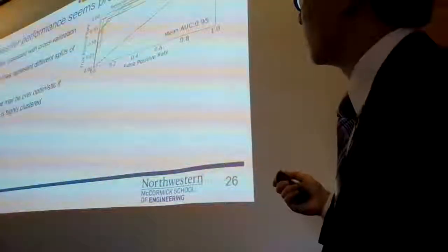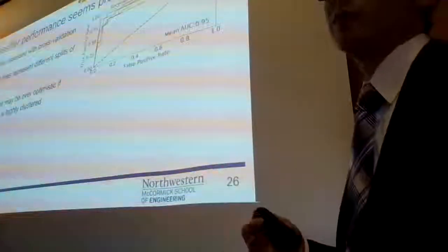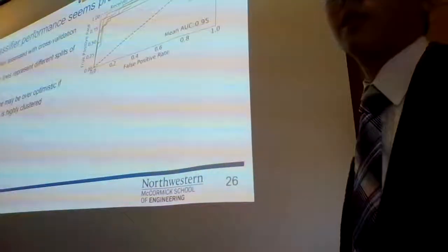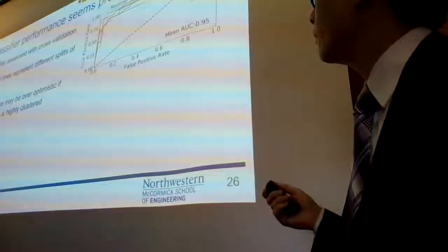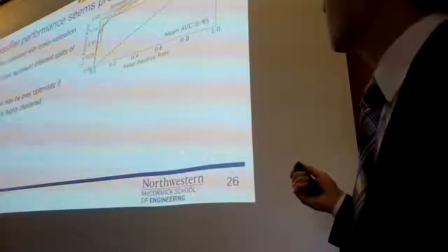And each of these curves here is from a different random split of the data being used as the test set, and me training the algorithm on the other, say, 5/6 of the data set. And we can see that while there is some variance, the performance overall is quite respectable, with a mean area under the curve of 0.95.